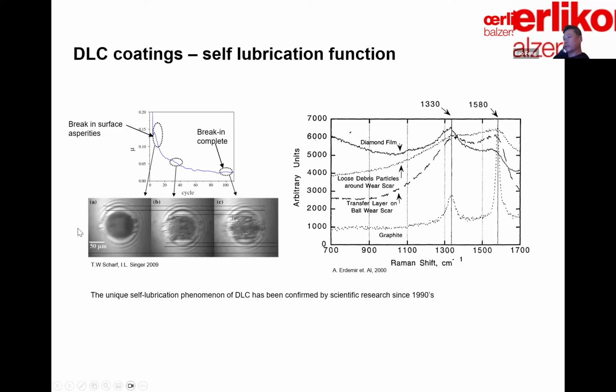What they were able to see was that during the breaking-in stage, there was a transformation in the transfer film from an amorphous carbon structure to a graphite structure. Of course, we all know graphite is a good solid lubricant due to its layered structure and easy shear. And we know many of those solid lubricants, like tungsten disulfide, moly disulfide, or PTFE.